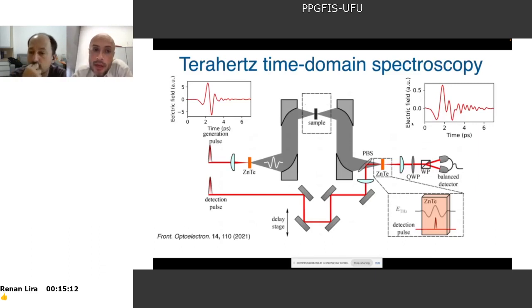One very, very important point here is that terahertz time domain spectroscopy allows you to measure the electric field, not the intensity. For example, when you measure photoluminescence or other techniques that measure intensity, you cannot collect the transmitted electric field. And because we can measure amplitude and phase of the transmitted electric field, we can calculate the complex refractive index, and as I will show you in a few minutes.